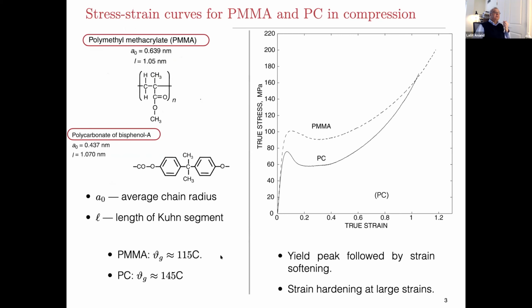One characteristic feature is I'm only going to talk about the response below the glass transition temperature. Actually, just for reference, for PMMA, the glass transition temperature is about 115, and polycarbonate is about 145 degrees centigrade. Okay, so if you take specimens of these materials and do a compression test.